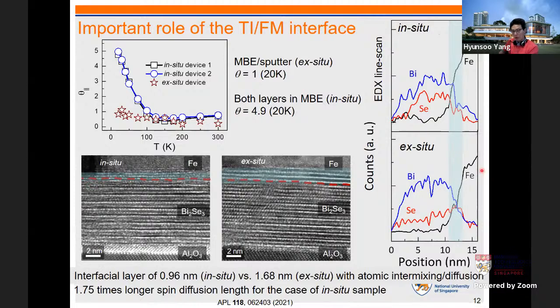So there must be something more about these scattered spin Hall angle values. And the other aspect could be temperature, because different groups reported the data at different temperatures. So first we investigated the temperature dependence. Then we found it can also vary significantly. If you look at this open circle, this is the in situ method. So we grow bismuth selenide and the magnetic layer in the same chamber without breaking vacuum, and you can see below 100 Kelvin there is an abrupt increase of the effective spin Hall angle.